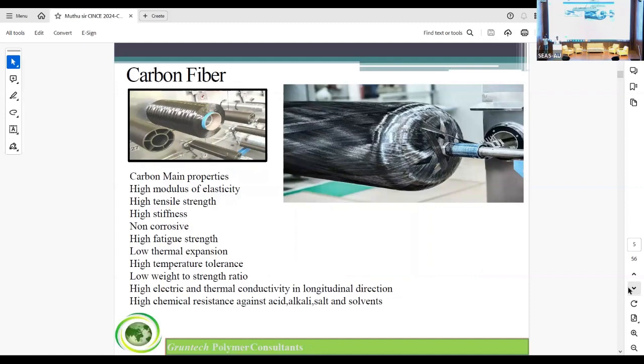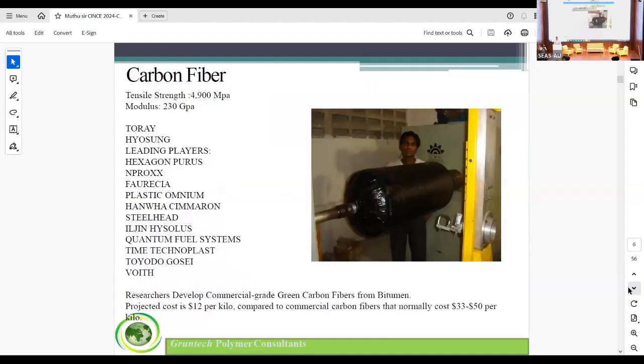Now carbon fiber. Why did we try glass fiber and basalt fiber? The thickness goes up, the weight goes up, and it does pass the burst test and hydrostatic test, but we fail fatigue. So that is the reason we moved to carbon fiber. You are all well aware of the main properties of carbon fiber since you are from the composite industry: high modulus of elasticity, high tensile strength, high stiffness, non-corrosive, high fatigue strength, low thermal expansion, high temperature tolerance, low weight to strength ratio, high electric and thermal conductivity in the longitudinal direction, and high chemical resistance against acid, alkali, salt, and solvents.